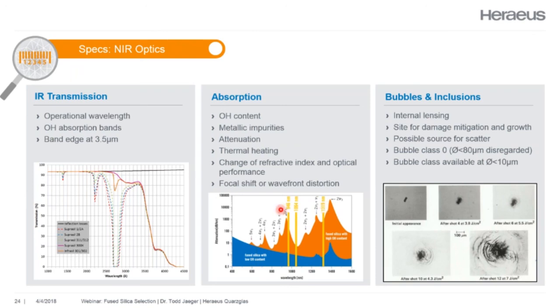What happens with that is that you get attenuation of the beam. This heats up the optic. You get a localized change in your refractive index or a heating of the entire optic, and your focal point will shift. So you're not machining where you'd like to be, or you have a distorted wavefront.